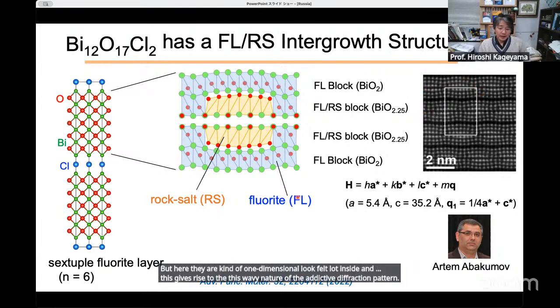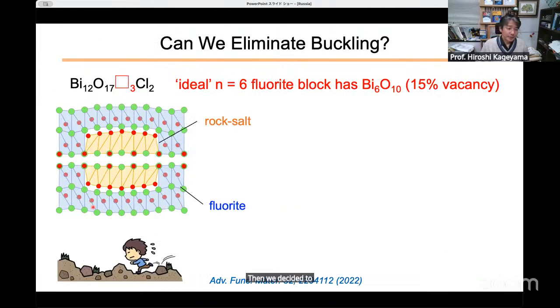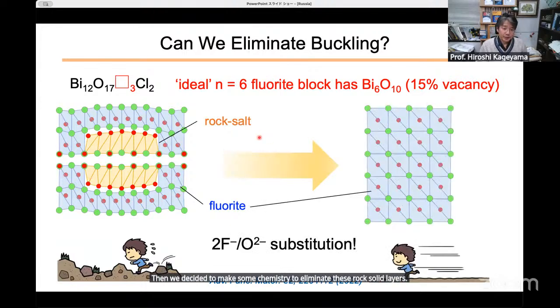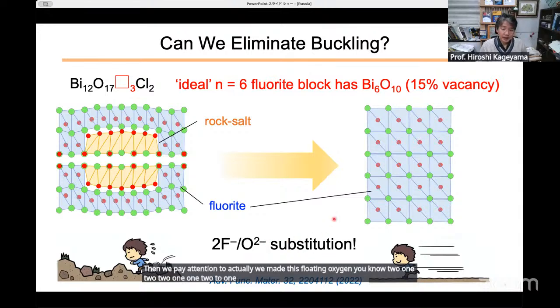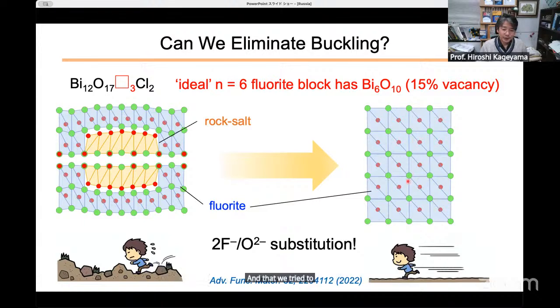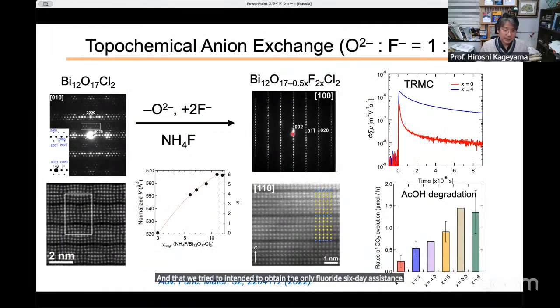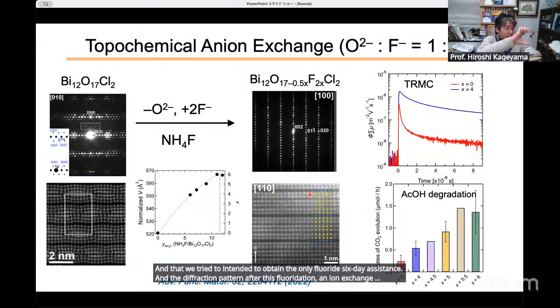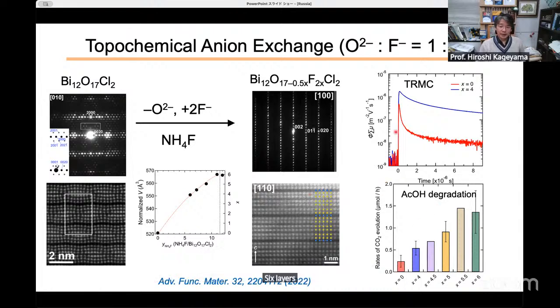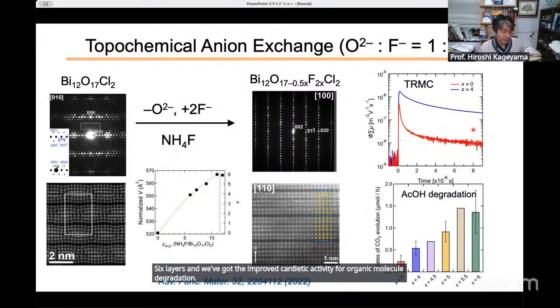Okay. Then we decided to make some chemistry to eliminate these rock-salt layers. We made this fluorine-oxygen 2-to-1 substitution chemistry, and we intended to obtain the only fluoride 6-layer systems. In the diffraction pattern after this fluorination, anion exchange reaction, we get the perfect flat 6 layers. And we got improved catalytic activity for organic molecule degradation reactions.